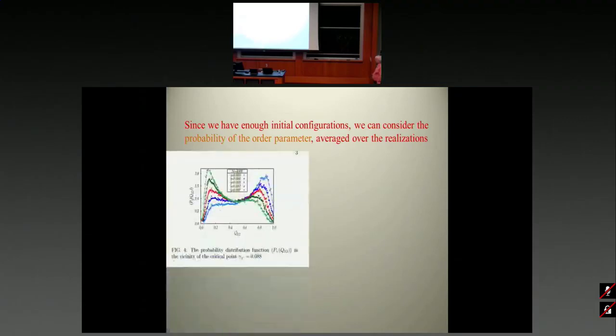Okay, since we have enough initial configurations, we can consider now the probability of the order parameter averaged over the realizations. What you see is the following. So now you look at the probability as a function of gamma of this Q12, and this is for various values of gamma near the yield. What you see is that before the yield, let's say at gamma 0.08, you have a big peak at the order of unity, and then it falls down.